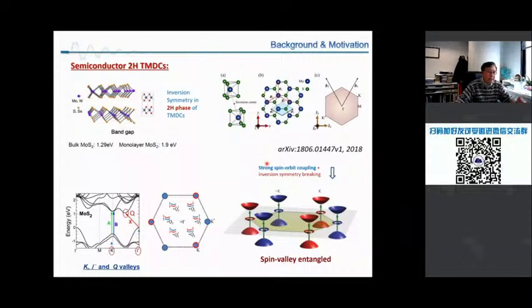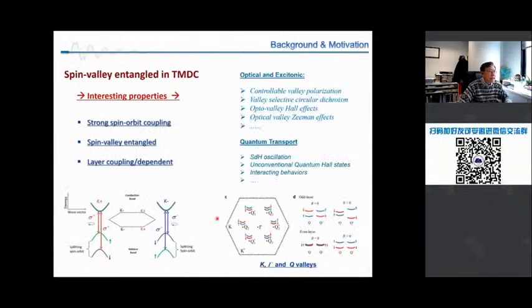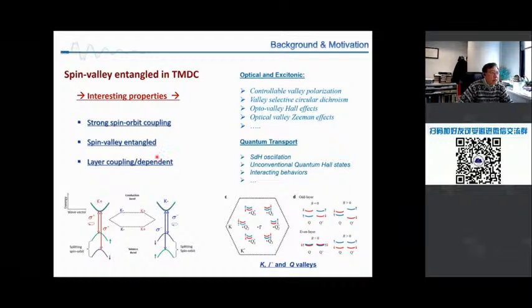Okay, for monolayer plus the inversion symmetry breaking, that causes the band splitting. Let's say for the conduction band, for example, at K, the spin up and spin down stay split, and at the valence band you have a similar situation. You may also call them left and right hand spin. So this strong spin-orbit coupling effect causes the spin-valley entangled states.